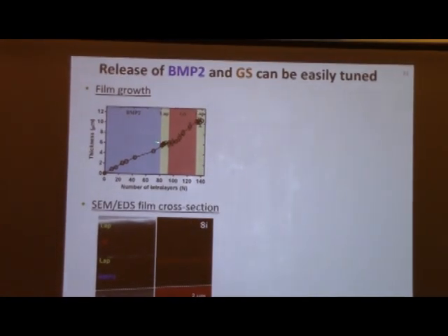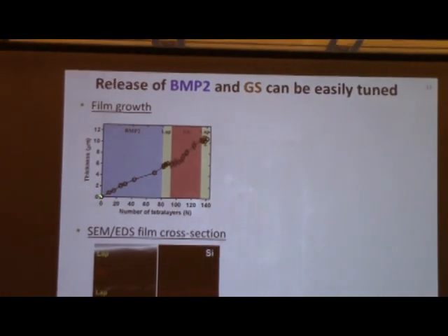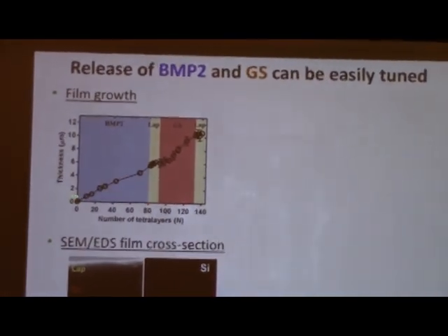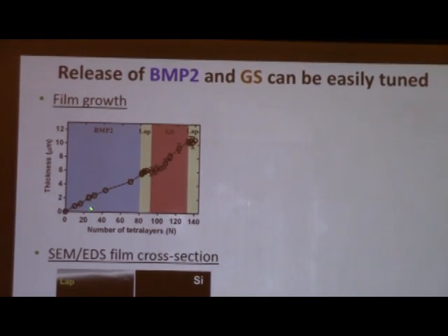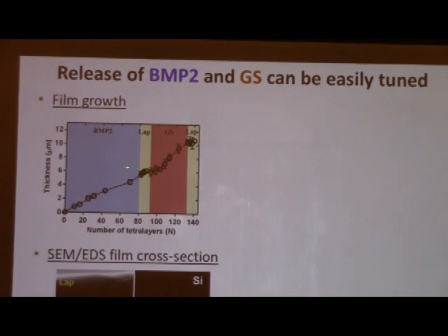So I don't know if you can see this as well, but on the left, what you're seeing is the growth, what we call the growth curve, when we're measuring the thickness of the film as we put down more and more layers of BMP2. And then we see the thickness of the film as we introduce some really thin layers of this laponite clay, just a small number of them. Finally, we build up the gentamicin sulfate, and if we want, we can even put a second set of laponite layers on top of the gentamicin sulfate. And now we have this very nice separated arrangement.